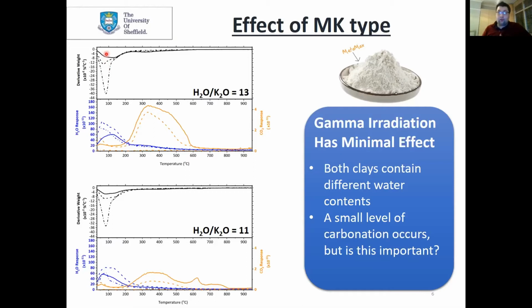Now this is the free water, the water within the pores, not in the structure. All this is really doing is filling those pores within the sample. So we've lost this, which is not a great loss from the system. But here we see on the shoulder of the curve, at around 175 to 200 degrees C...